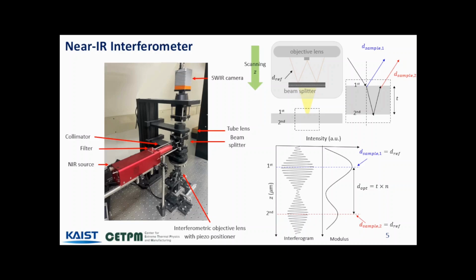interference patterns are obtained for each interface, allowing the reflected light from each layer to be distinguished. The relative position of each layer is determined by the interference maximum. Since the optical distance is the product of the channel height and the real part of the refractive index, we can extract the real part of the refractive index using the known channel height.